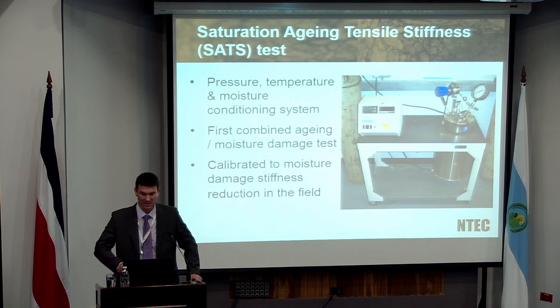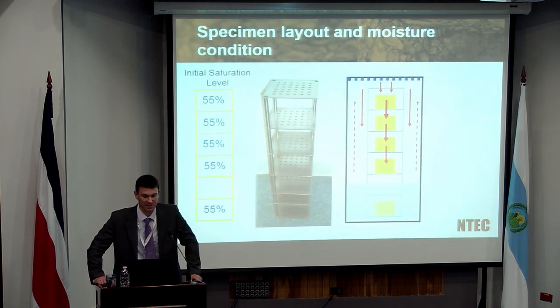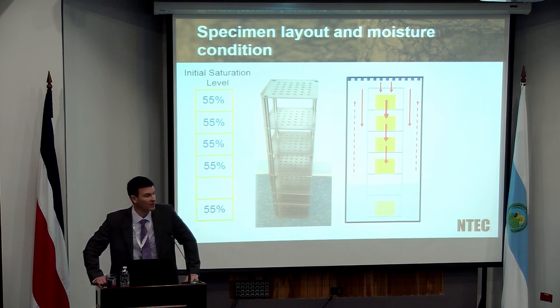We then place those different specimens into that particular loading frame. That loading frame allows us to place inside a pressure vessel 4 specimens above a water reservoir. At the bottom of that pressure vessel, we place a small amount of water and allow one of those specimens to be submerged. So what we've got now is 4 specimens above the waterline, 1 directly inside the water bath. And then we apply pressure, and the pressure is quite high. It's about 20 atmospheres, so very similar to what you would use when you're doing your pressure aging on your binders with the PAV. And it allows us to obviously increase the temperature. So we've got 2 mechanisms, a pressure and a temperature mechanism, reacting to that particular set of specimens.